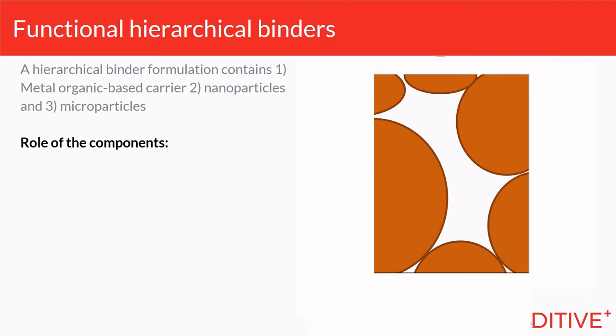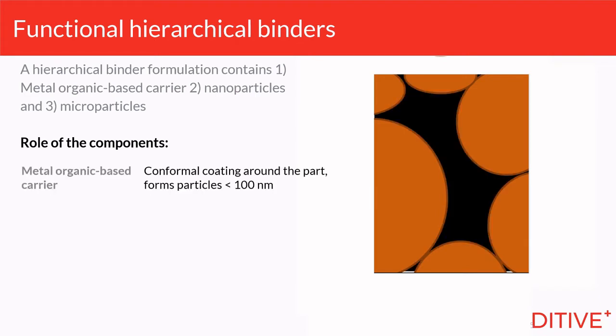So what we developed at Liverpool was we got rid of that sacrificial polymer, and instead of having a polymer, we used a binder that was functional. So it was made of functional material. And we call it hierarchical binder because it contains 3 components. And the first is a liquid. It's a metal liquid. It's a metal organic. And when that is jetted onto the powder bed, it forms this conformal coating of a metal or ceramic, depending on what material you're using. And that film acts like a cling film and holds the powder together in its 3D structure.